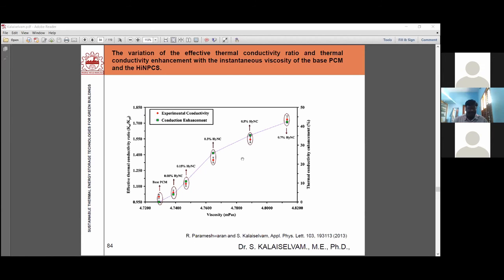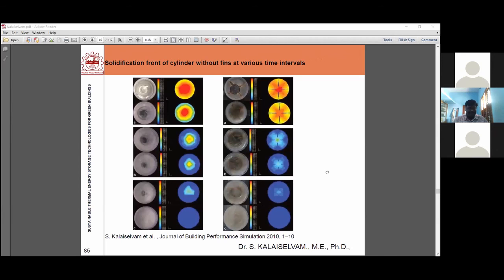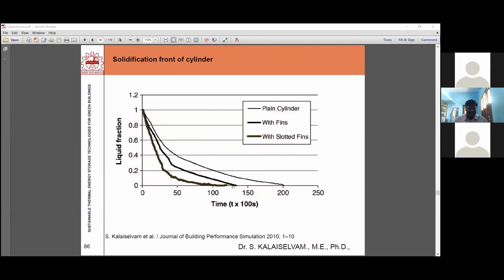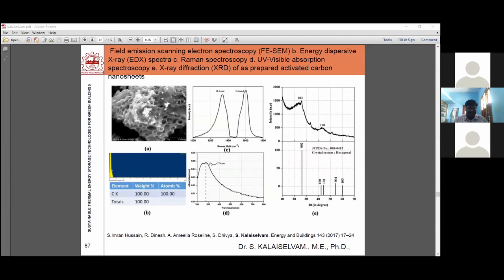This is again the thermal conductivity. You may have asked whether, instead of going for a nanomaterial, we can also put fins into the ball. We also tried that, and obtained the results. We concluded that instead of putting in fins, if you put in a nanomaterial, much more enhanced results may be obtained.